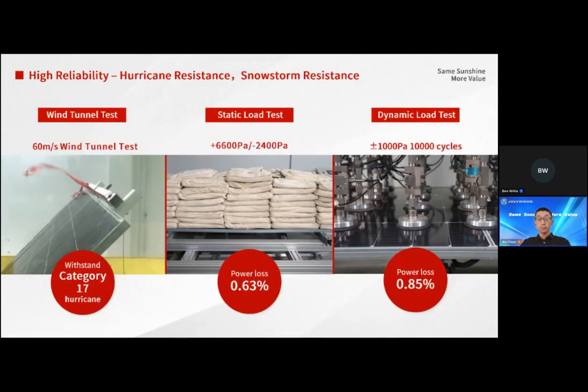The windproof module has been rigorously tested for resistance to high winds and storms. It passed the 60 meter per second wind tunnel test, equivalent to a Category 17 hurricane. Also, the windproof module underwent rigorous testing, including static load of 6,600 Pascal on the front side and 2,400 Pascal on the back side, as well as dynamic load testing of 1,000 Pascal on both sides for 10,000 cycles, demonstrating excellent resilience in extreme weather conditions.